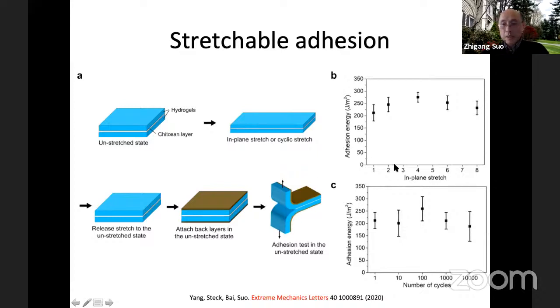After in-plane stretch, for different amounts of stretch, up to 8 times stretch—enormous stretch—adhesion energy hardly changes, you can see that. And also we do cycling: after 10,000 cycles of stretching back and forward, adhesion energy hardly changes. It's a very stretchable adhesion, not a problem.